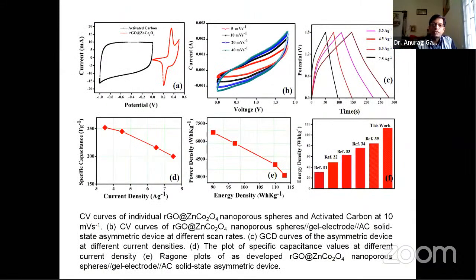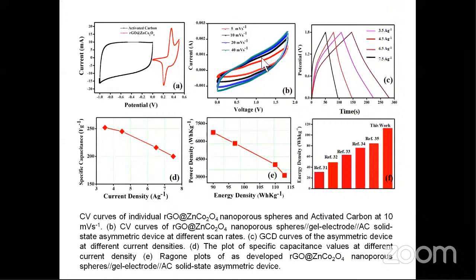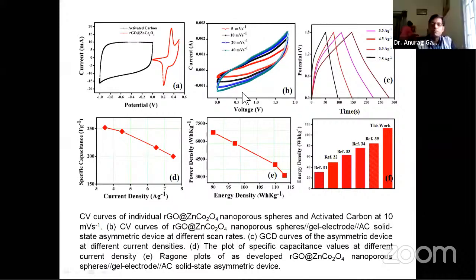So these are the CV curves for that. Here you see that now we are using activated carbon, so there is a dominance of EDLC behavior in the CV curve. You can notice that, but still it is not purely EDLC. It is pseudocapacitive, so non-linearity is there in the GCD curves. Then you can see the energy density for this, which is around 115 watt hour per kilogram. That is very good and approaches the battery side.